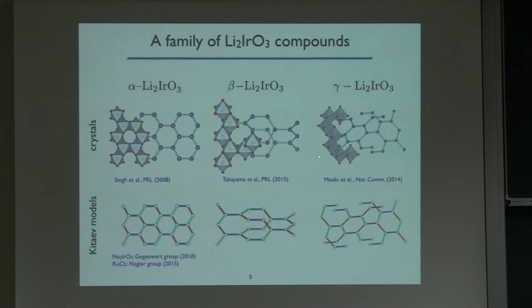The important feature is if you look at an iridium site here, it still has three nearest neighbors. And you see there's really a perfect 120-degree bond angle between them. So that's the first thing, it's tricoordinated. The next feature is you still have this edge-sharing octahedra structure. So this now gives us materials that should realize the Kitaev model on a three-dimensional lattice. And we realize we already have two different three-dimensional lattice structures that we can consider.